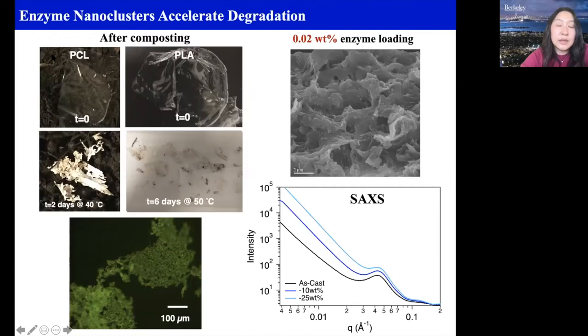This one is PCL, and that is polylactic acid. Those are two commonly used biodegradable plastics. And we basically embed the enzyme in them, and then we just put them into the dirt to see it. And the PCL degrades a little bit faster than PLA. PLA takes, I would say, this is after 6 days at 50 degrees. It takes about a few weeks for us to no longer find it, and both of them are degrading.